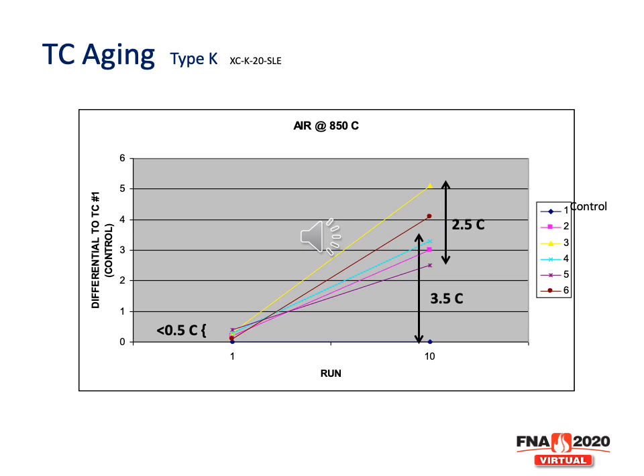Then what we did is held one back, the number 1 TC, the control one, and ran the other 5 of them down through the furnace on multiple runs. After we got done with that, we said, let's see how much they may have moved from the number 1 TC. So we put them all back together again on run number 10. And what we found is those 5 thermocouples were now 2.5 degrees C apart, and they had moved 3.5 degrees C from the original TC. So that's an issue that you can have with repeatability.